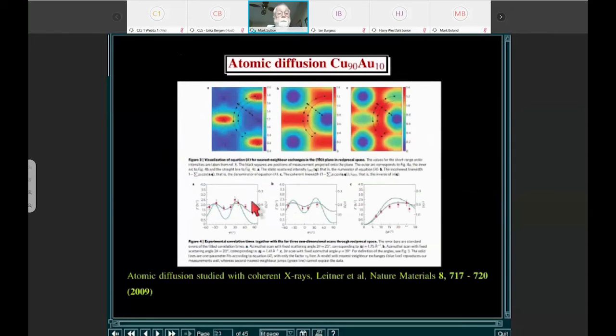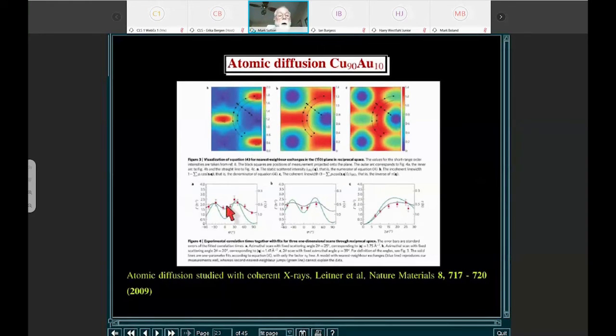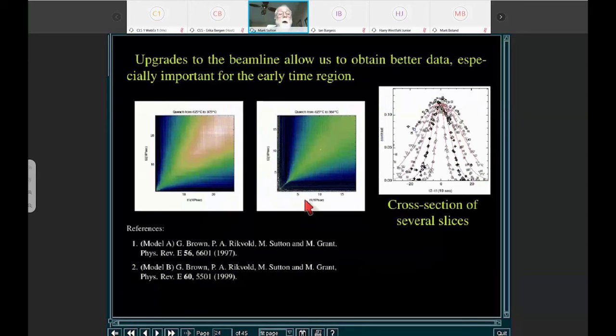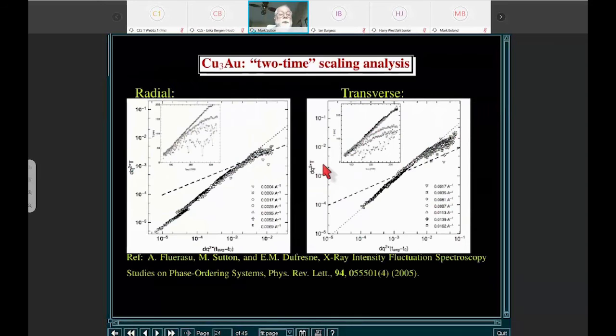Here's an example where you look between the Bragg peaks of copper gold in this case, and you can measure the time constants, which are very long. They're minutes and hours long here. And you can look at different models of the hopping probabilities for diffusion, and you can get an understanding of how the time constant varies across the Brillouin zone. Here's the copper-3 gold, where you can see the time evolution of the time constants.